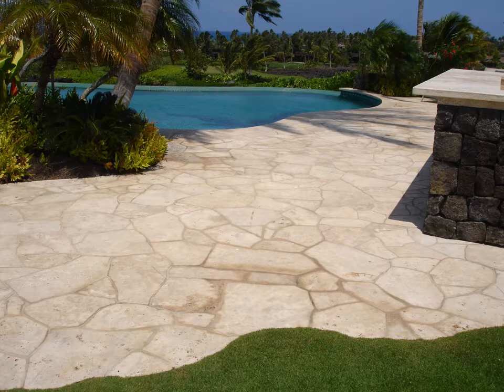This is a travertine flagstone pattern, just showing next to a landscaped area in the foreground here, where the irrigation has oversprayed. There's a low spot in the floor here, which is allowing a puddle, what we call a bird bath. And when the water dries, it goes into the sky, but the minerals stay behind, and over time they form this dark mineral stain. This area here is kind of reclaimed water used for the irrigation. And it's very, very high in silica, so these stains form very quickly in this certain resort neighborhood.